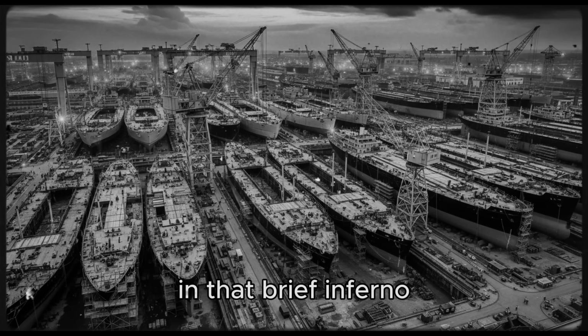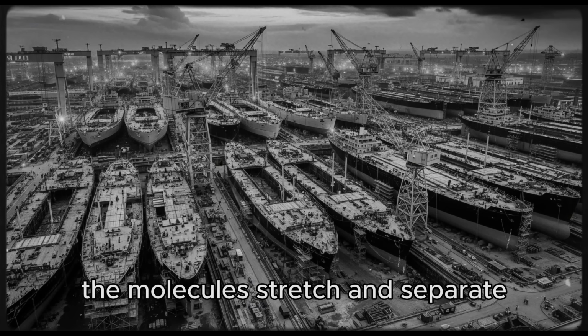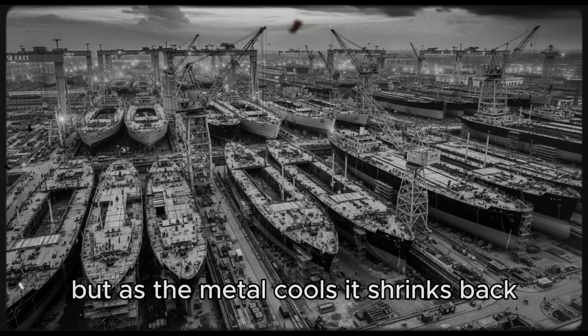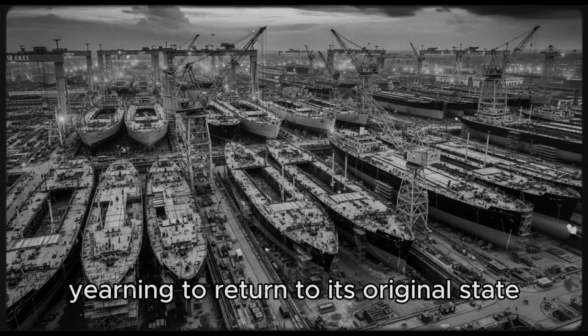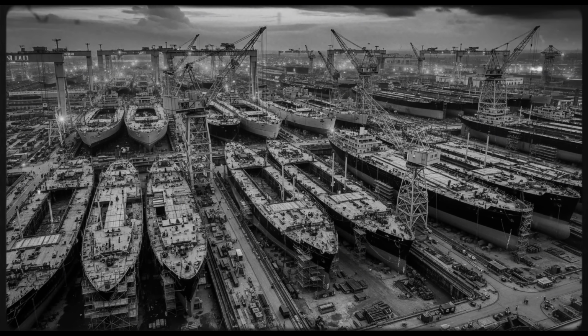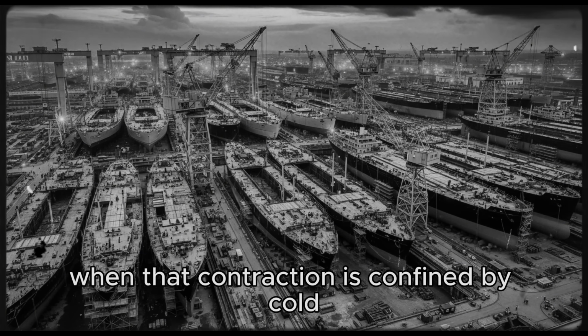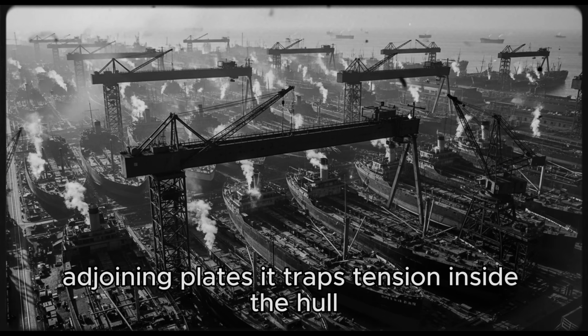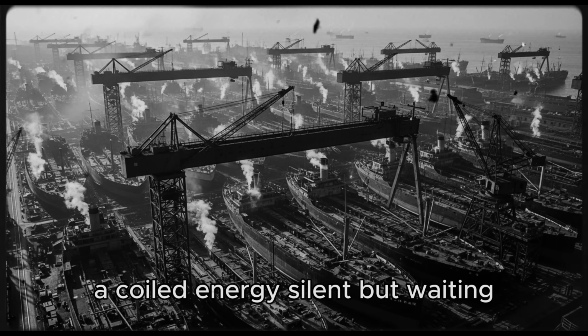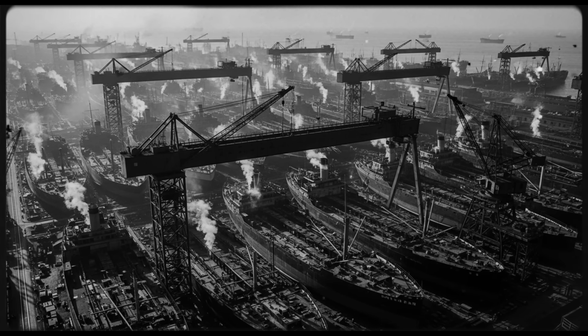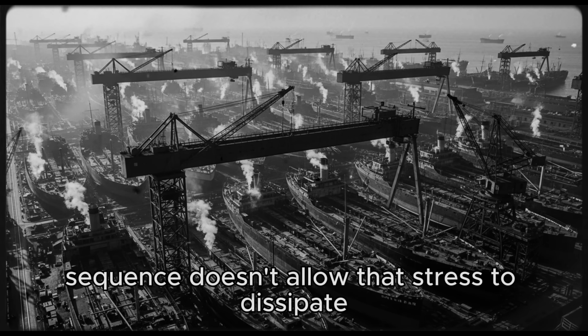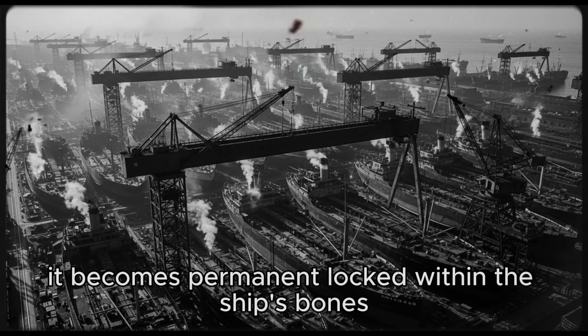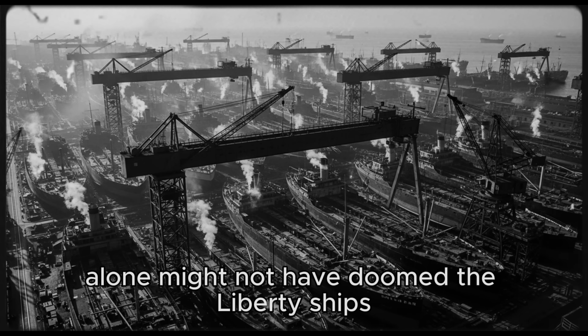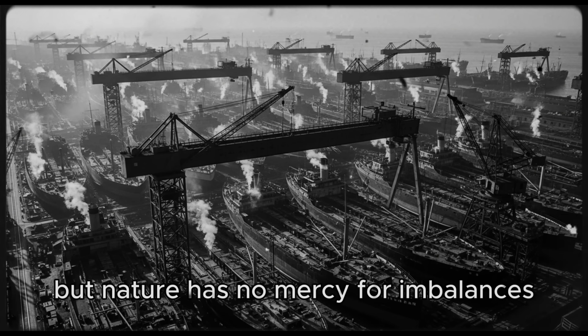In that brief inferno, the molecules stretch and separate. But as the metal cools, it shrinks back, yearning to return to its original state. When that contraction is confined by cold adjoining plates, it traps tension inside the hull, a coiled energy, silent but waiting. If the welding sequence doesn't allow that stress to dissipate, it becomes permanent, locked within the ship's bones. That hidden strain alone might not have doomed the Liberty ships, but nature has no mercy for imbalances.